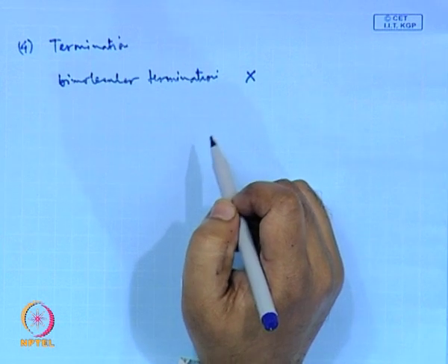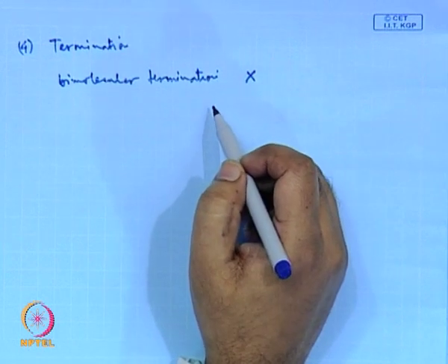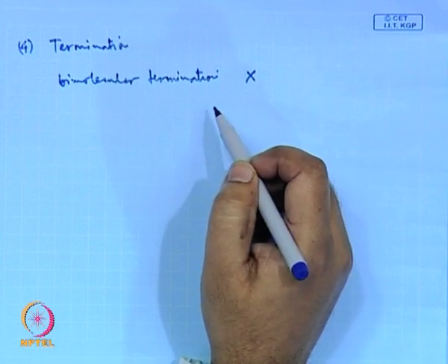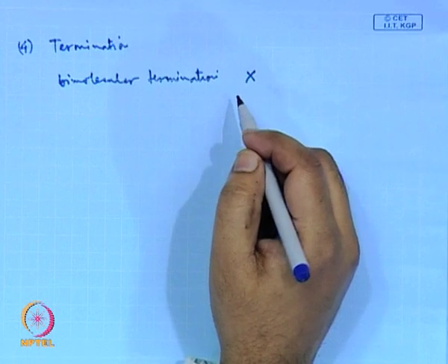So if you can suppress the other reactions, which are chain transfer reactions, you can keep these ionic chains living, because the intrinsic termination reaction between the propagating species is absent.